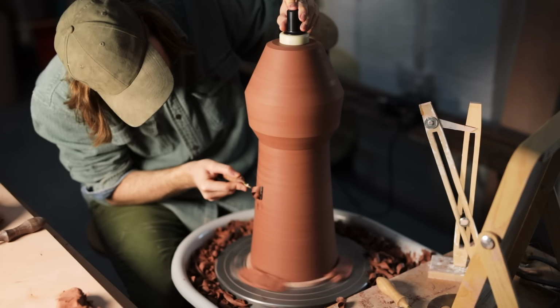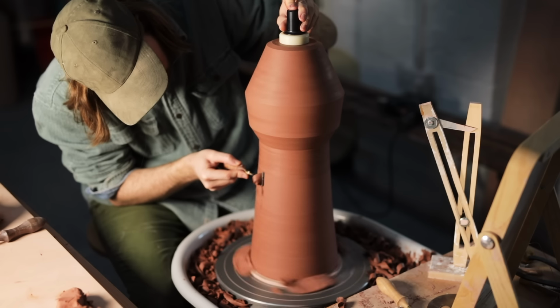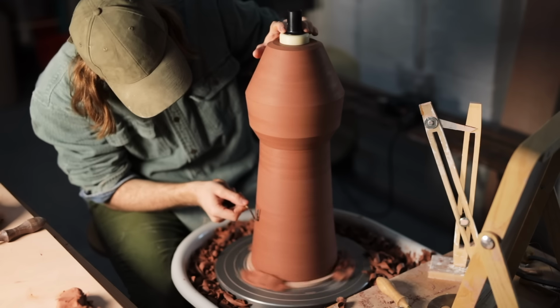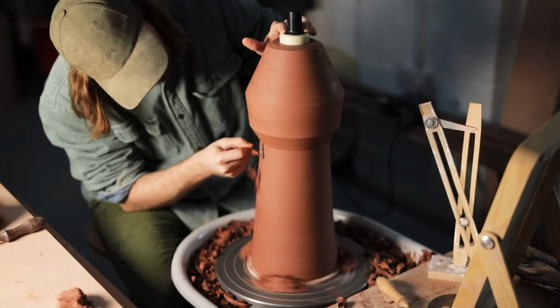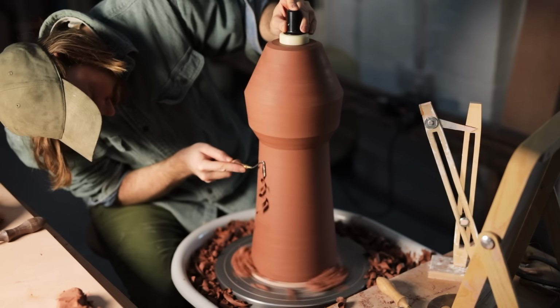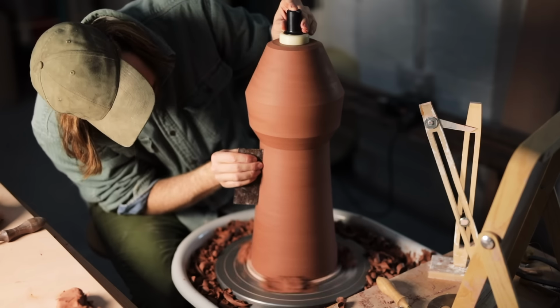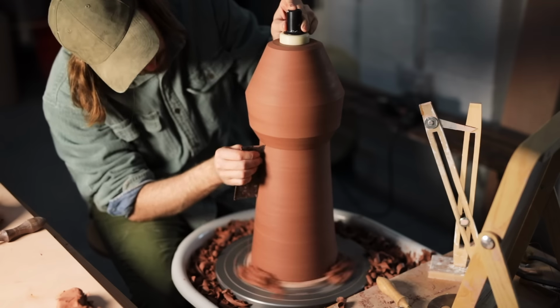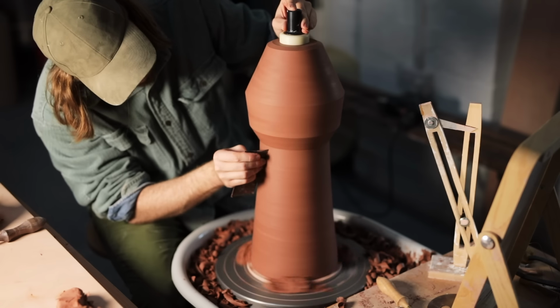And this meant, especially if that inconsistency was on the very lowest section of the pots, that all that clay above it would overwhelm that thin spot, causing it to crumple like paper, especially when fired exceedingly hot to cone 10 or some 1290 degrees Celsius.